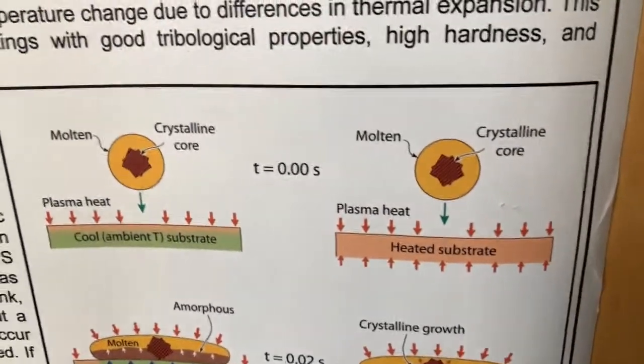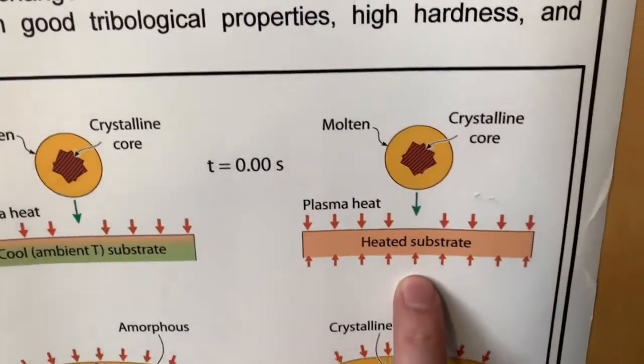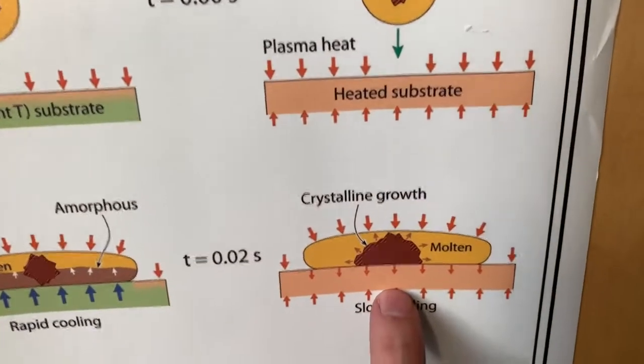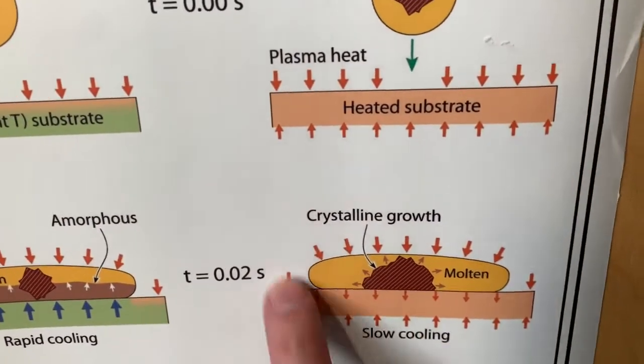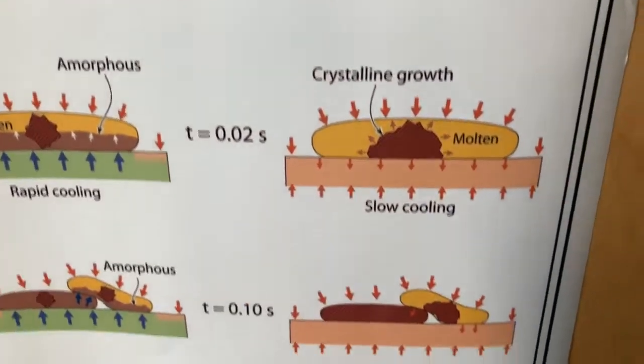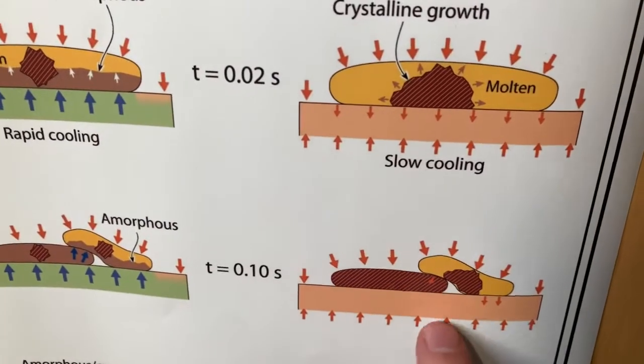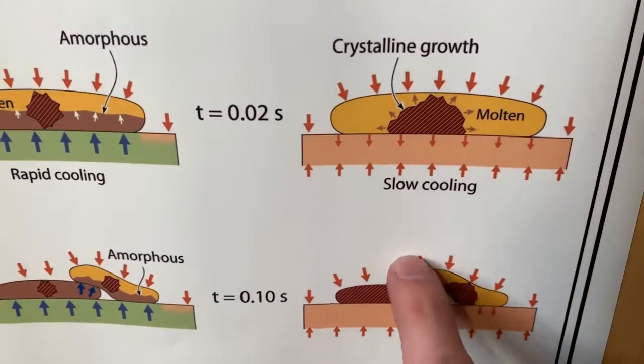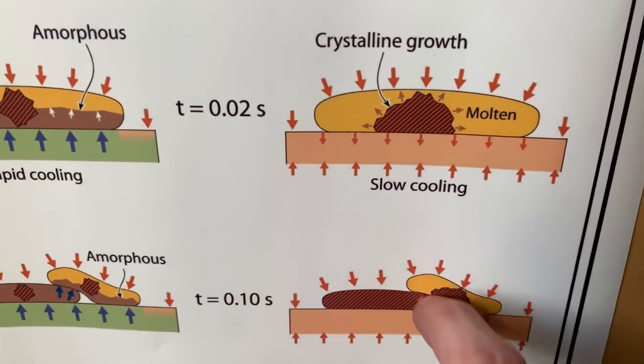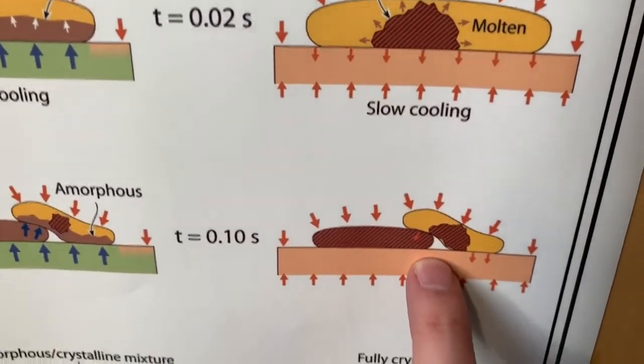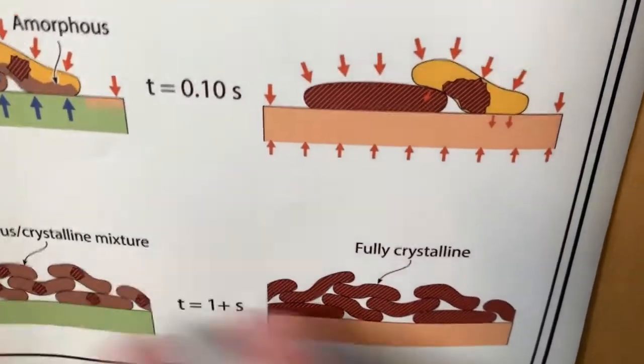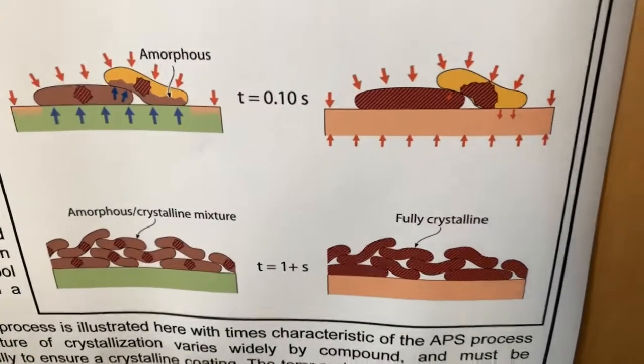On the other hand, when you do it on a heated substrate, you will not have that rapid cooling, and instead you're going to start growing a crystalline material. And when that grows, all these pores that you see here, because the rest is still molten, it might actually creep in there, and you can fill up these pores until you get a fully crystalline, or at least mostly crystalline material.